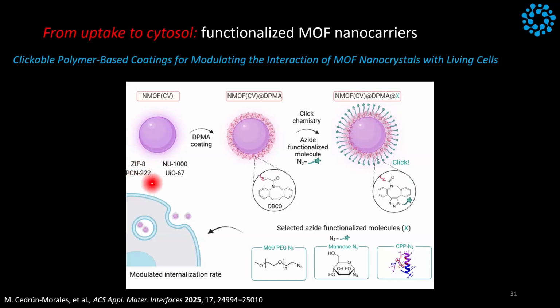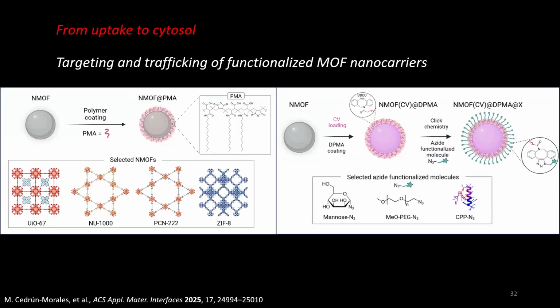And I asked her to compare ZIF-8, NU1000, PCN222, and UIO67, different chemistries, different systems in the nanoscale, to grow on top of it either PEG or this PMA. In this particular case, it was a polymer with a cyclooctyne group to do click chemistry on top of the MOF. So basically, once you have this cyclooctyne, I asked her to put some PEG, some mannose, and some cell-penetrating peptides. This is a long story, this cell-penetrating peptide, but it's supposed to be very efficient in bringing nanoparticles inside a cell and follow some routes that I don't have time to explain. So she did that. It worked very well.